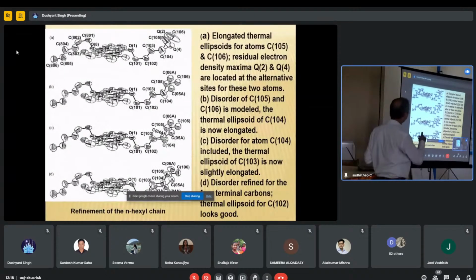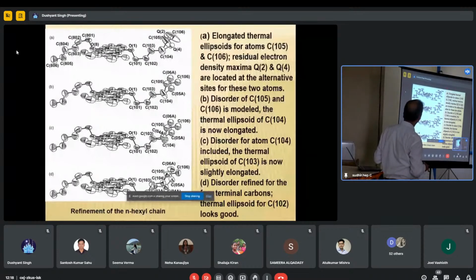Now I have taken one example. Firstly, when I solved the structure, only these two atoms, the terminal atoms of the hexyl chain, were showing disorder. Say it is a liquid crystalline material. All other atoms had almost the same thermal ellipsoids. When I resolved these two by bifurcating into 4 parts, 1, 2, 3, 4, you can now see that C104 is not showing disorder. Only C105 and C106 were showing disorder, and their shape is such that they are showing disorder.